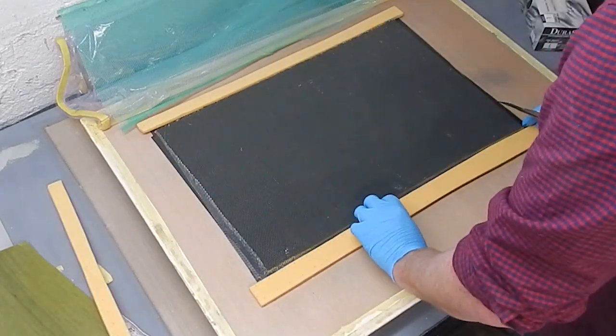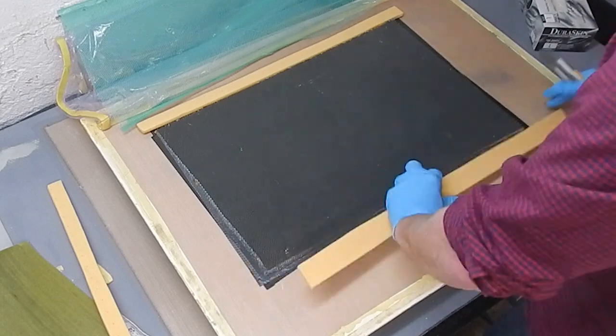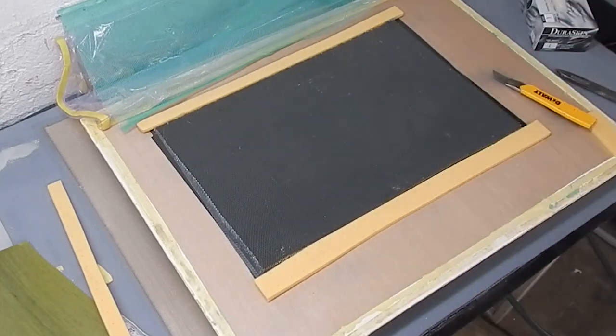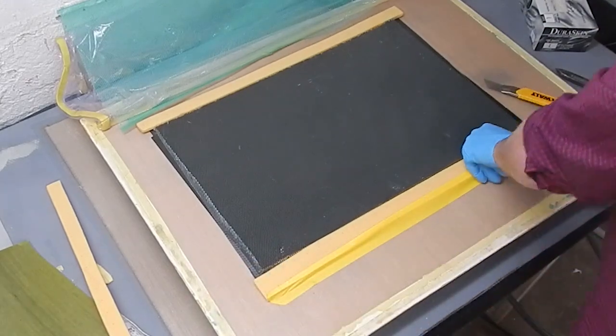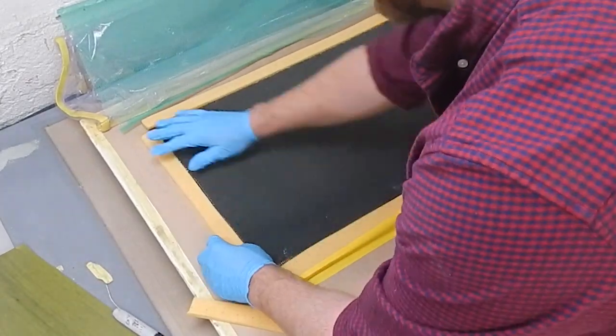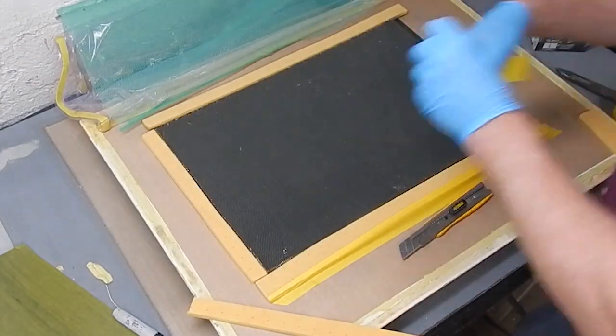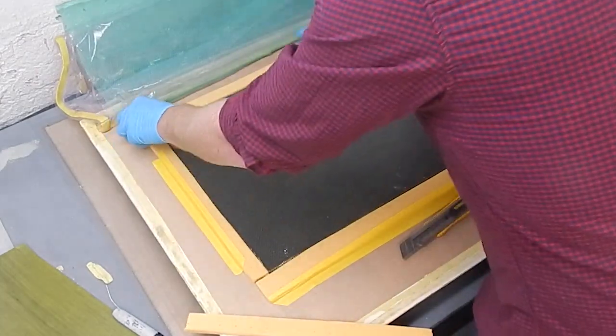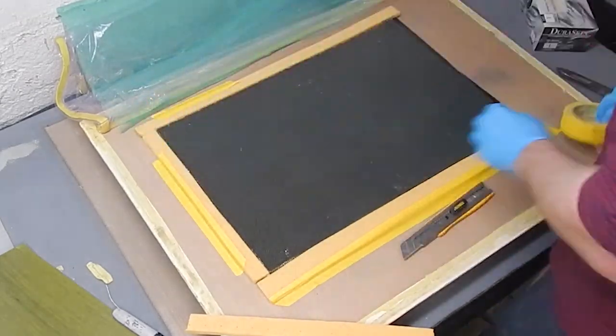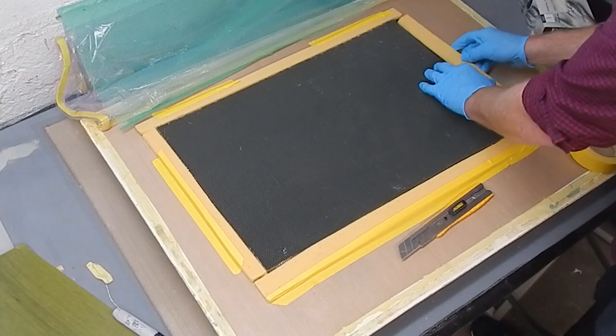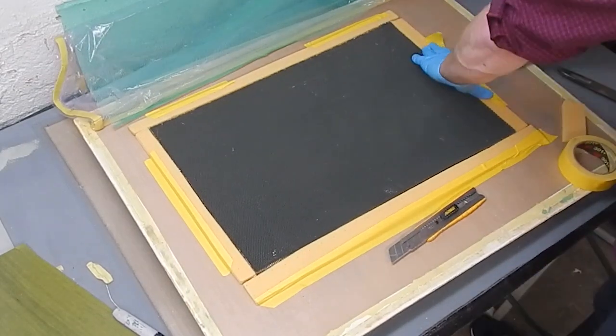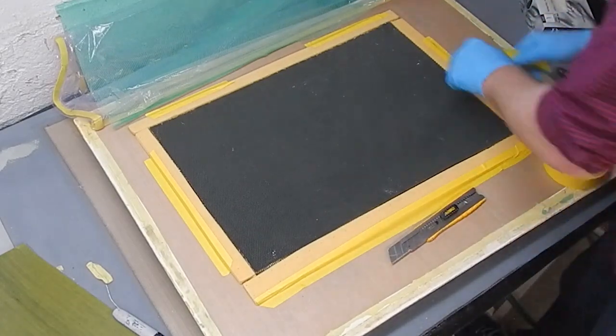And to keep the edge of the honeycomb from crushing, I'm using some foam strips of about the same thickness that are sacrificial. They just go around to make it easier to demold and to keep the bag from pushing the honeycomb in, messing up the edges. This could be done with wood or aluminum or foam, pretty much anything. Foam is nice because it doesn't hold a lot of moisture. And I had some just sitting there like cut strips off of. The tape is really to protect the bag and hold everything in place.